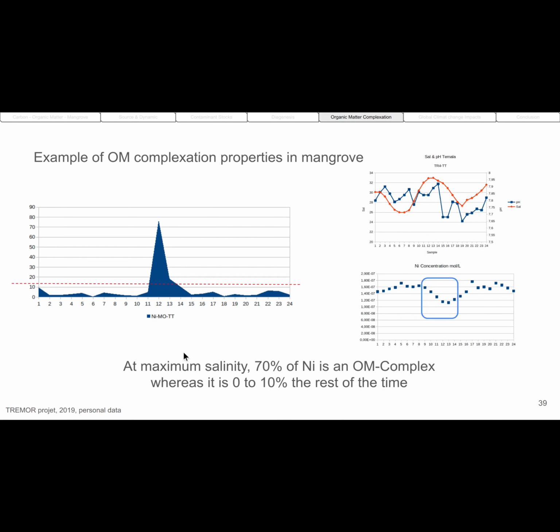And you can observe that during the high tides, up to 70% of nickel is complexed. And it corresponds to the lower quantity of nickel in the water. So this means that during this high tide, we have the production or appearance of organic matter that complexes more of the nickel in the system. And the rest of the time, it's 0 to 10%. So there is a reaction of the mangroves to the system, and when there is less nickel, it complexes more nickel.